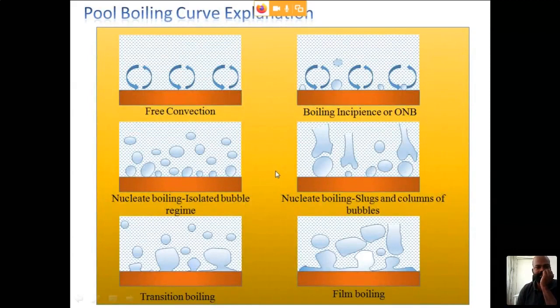Here I have given a pictorial representation of the individual activities taking place right from free convection to boiling incipience. Here you can see the initial bubbles are generated randomly at very few spots. But as the heat flux increases, you can see the isolated bubble region where more bubbles are initiated. The concept is that the number of bubbles generated, or the nucleation site density, increases with the increase in heat flux or temperature, and as it decreases, the activation of the cavities also decreases.